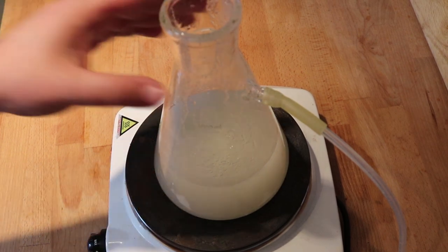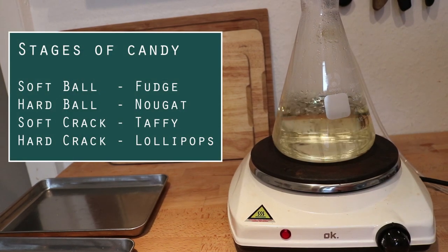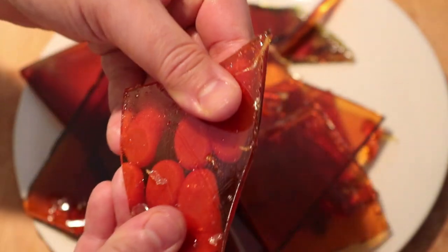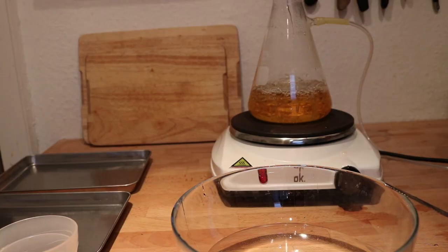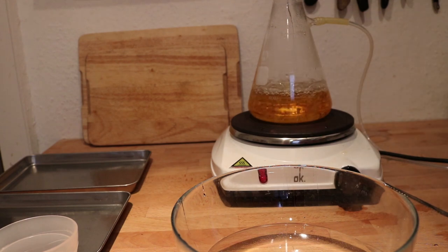The process for making sugar glass is essentially the same process as making candy. We just need to bring the sugar up to the hard crack stage. Hard crack stage in terms of candy making means that we just need the sugar to be around 145 degrees Celsius or 290 degrees Fahrenheit. As the name hints at, once the sugar is heated up to this point and then cools back down, it will crack like hard candy. So we're just going to let this heat up on medium-high heat. There are actually two methods to see which stage in the candy making process you're at. The first and perhaps easiest method is just to use a thermometer — we just need to see that the sugar is getting up to 145 degrees Celsius. Since I was a doofus and used this flask, measuring with a thermometer in this flask setup actually gave me steam burns.